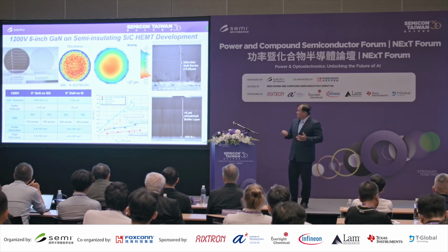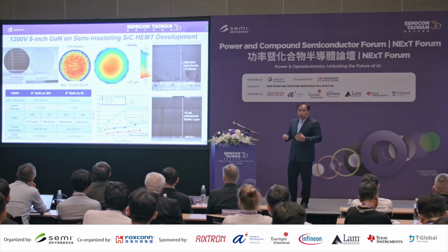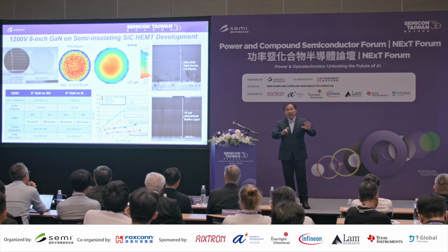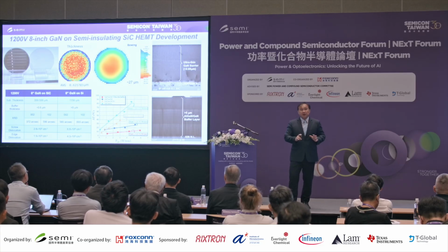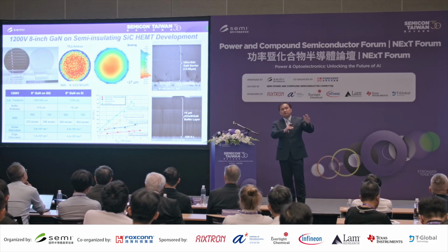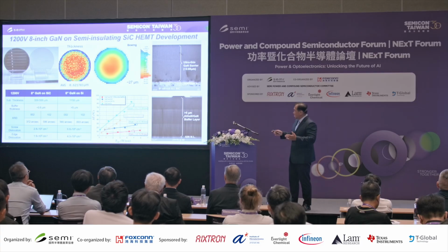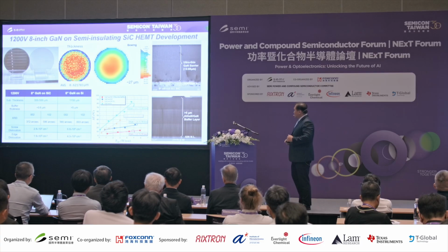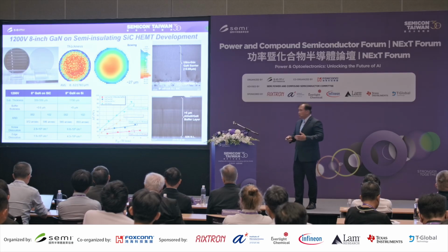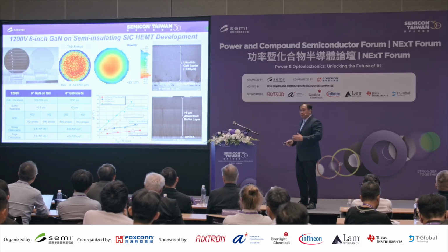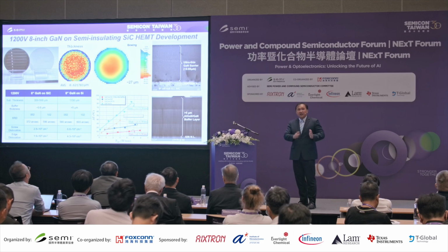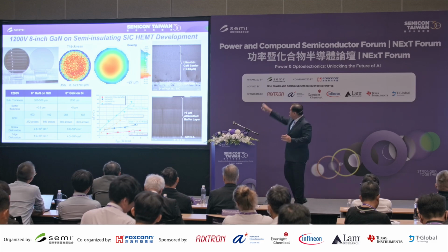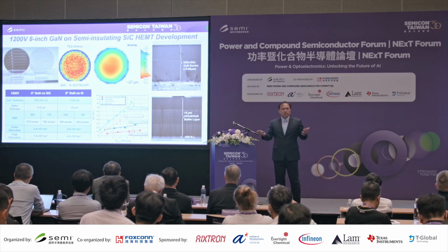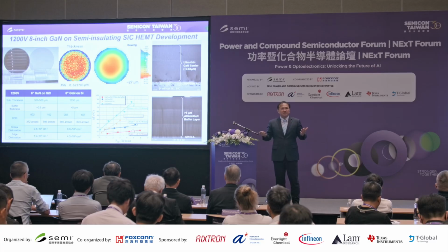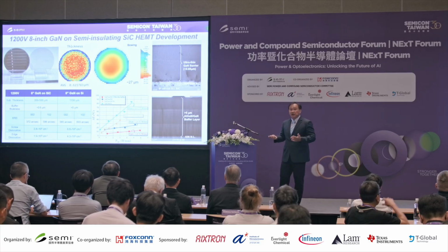So I eventually find that for GaN on silicon, from gallium nitride to silicon, you have an 18% lattice mismatch, but it's only 3% for gallium nitride to silicon carbide. So it means for the buffer layer thickness of GaN on silicon, if you want to do 1200 volt, you have to grow by MOCVD more than 5 micron, because 1 micron of gallium nitride can offer you 250 volt. But for silicon carbide, actually the voltage is blocked by the semi-insulating silicon carbide substrate instead of the gallium nitride buffer.